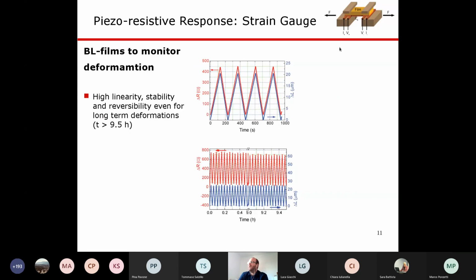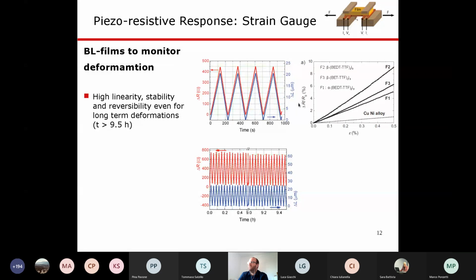In order to do that, we cut a small piece of this plastic and we mount it between two electrodes, and then we deform, or we stretch, these electrodes in a horizontal direction as shown here. In this picture over here, you can see in blue, this is the elongation. It's around 20 micrometers, it's very small, but the electrical resistance change follows very nicely. We can repeat this for really long times, almost up to 10 hours, and there is almost no degradation.